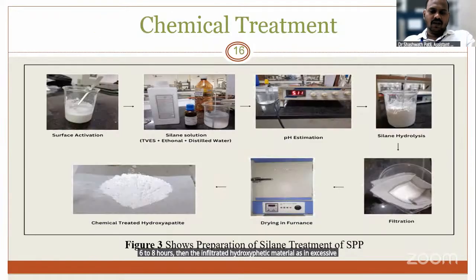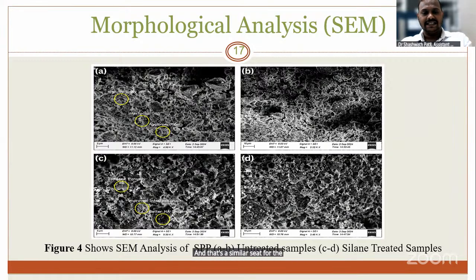If you look at the major difference I have attained between the untreated and treated material, images A and B show the untreated samples and images C and D show the silane treated samples. As you can see in A, there is high porosity from the SEM image, an interfacial gap, and the particles get accumulated. But when we did this silane treatment, the porosity was reduced, the interfacial bonding improved, and the hydroxyapatite had better dispersion. There was no particle accumulation present.